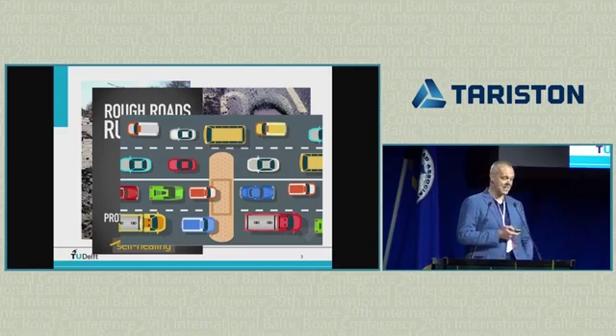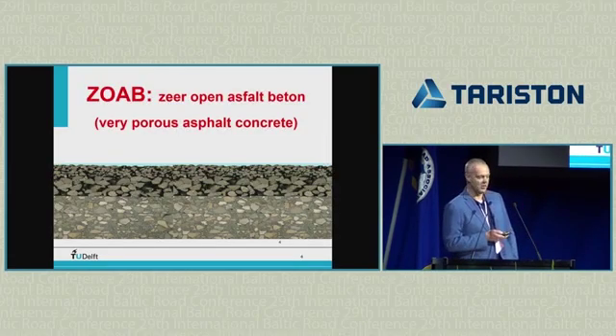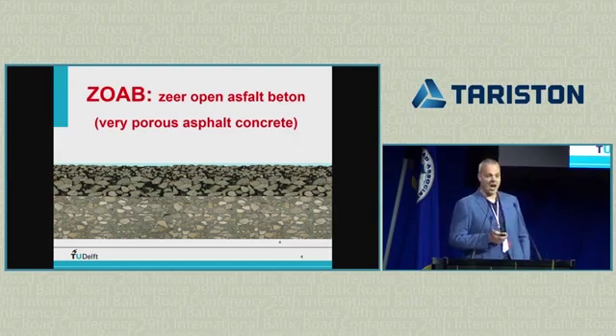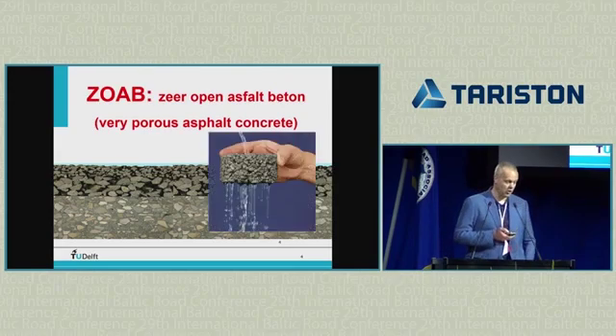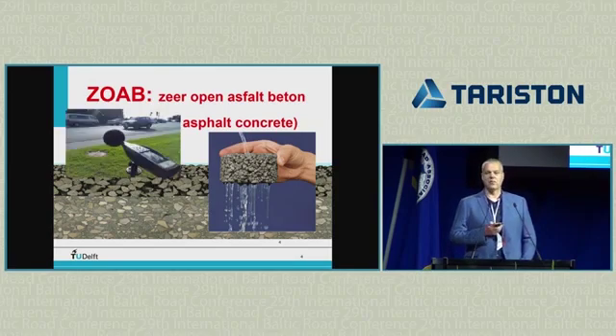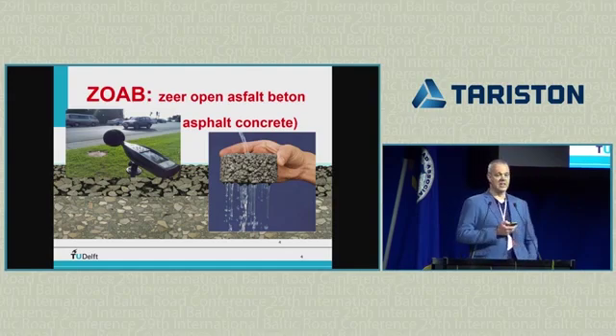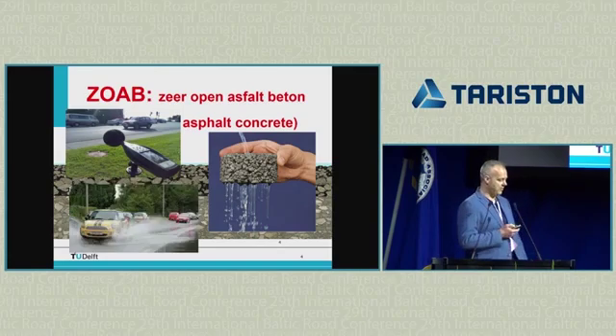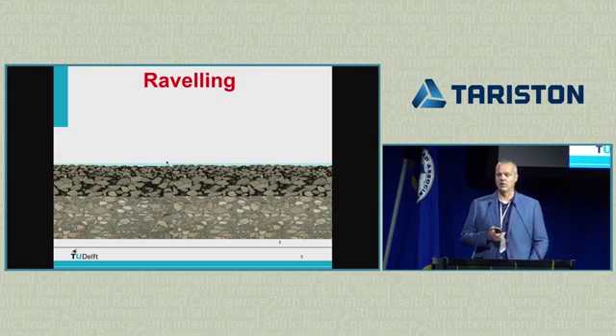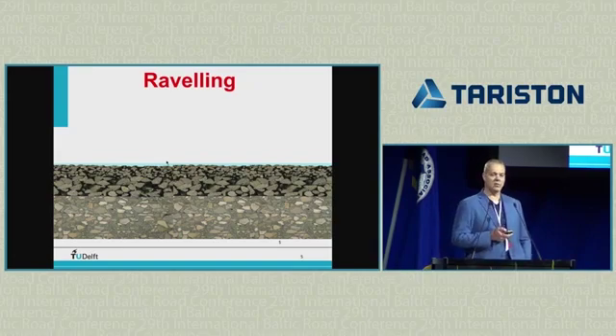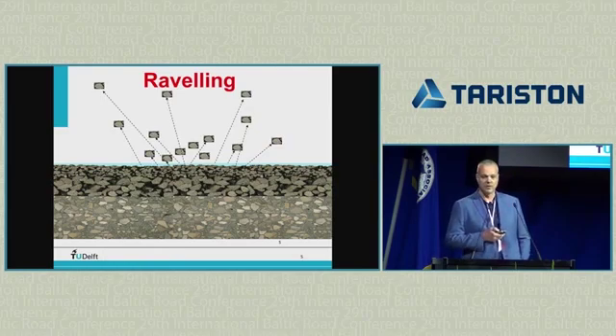We can use a plaster as shown here, but we developed some more interesting techniques that work better. In the Netherlands, a lot of our road surfaces are covered with zoab, which is a very porous asphalt. Most of the highways have this as top layer, because it's a very good asphalt: it's draining water, and it's also absorbing noise. So it's a very good road to drive on. But the durability of this top layer is not that good, because every benefit comes with something negative. The driving conditions are perfect, but we have a mechanism in this asphalt called raveling. This mechanism also happens in dense asphalt roads, but especially in porous asphalt roads we have a lot of raveling, which means the stones coming off of the surface. And this we want to prevent.